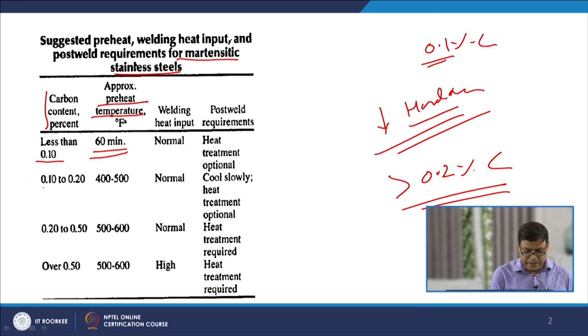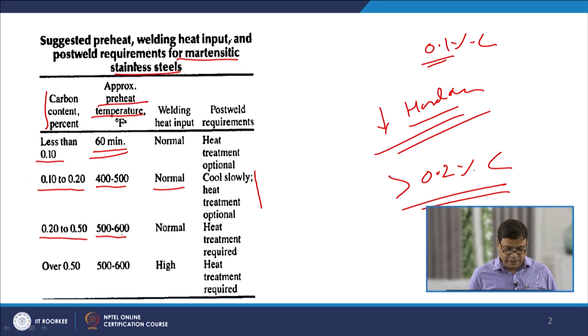And when the carbon content is in the range of 0.1 to 0.2%, then a preheat in the range of 400 to 500 degree Fahrenheit is used with normal heat input, and we need to use slow cooling after the welding, and heat treatment is optional. When the carbon content is in the range of 0.2 to 0.5, then a very high preheat temperature is used, like 500 to 600 Fahrenheit, and in this case post weld heat treatment is important in order to relieve the residual stresses and induce the toughness and the required mechanical properties.